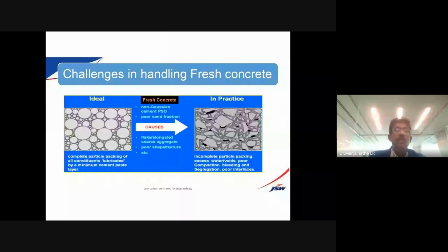So, challenges in fresh concrete. When we make concrete, we are going to get a lot of challenges. Whoever is making concrete, definitely we are going to get many challenges. Challenges in the form of, when you make concrete, mainly workability is very important, and shrinkage cracks, plastic shrinkage cracks. So we need to avoid all these things. In practice, ideally we need a perfect particle packing, but in practice we get excess water, bleed, compaction issues. However, if you're not coming from a good quality ready mix batching plant, if you're making concrete at site, whatever may be the thing, it will be affected.